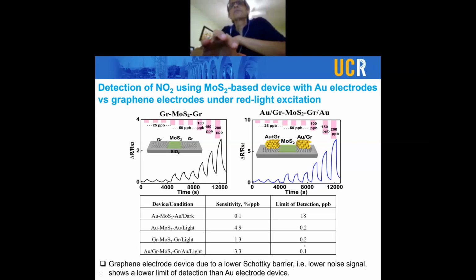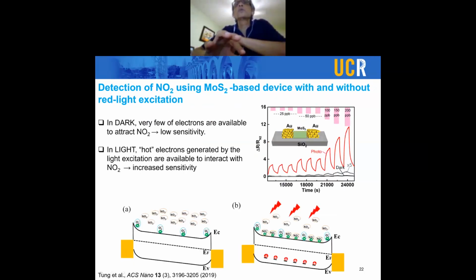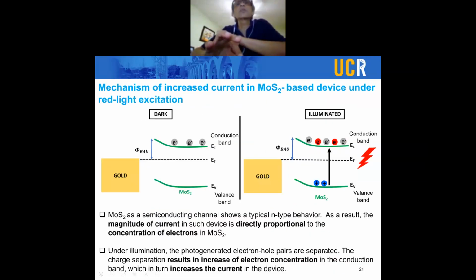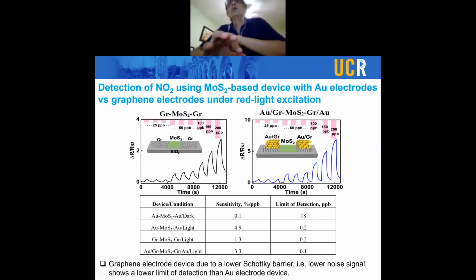So here's a comparison of all the NO2 sensing we did. The sensitivity of the gold MoS2, gold with the light, is higher than the graphene MoS2 graphene, but the limit of detection is better for the other one. And the reason for that, if you had paid attention, is the signal to noise ratio. I don't have the figure showing that here.